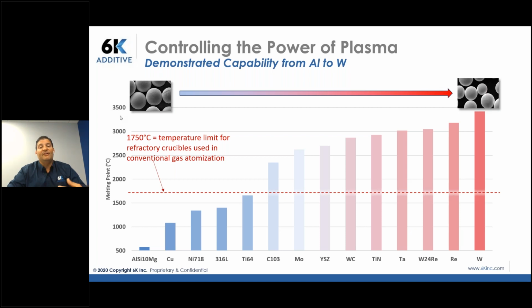And we can be successful with all of these because of that control that we have over the microwave plasma system. And there's a few different ways to control it. We can control the power, and we control the space where we actually inject the material into the plasma. But what it allows us is, again, anywhere from a very low melting temperature material all the way up to a very high melting temperature material to be processed through this system. So again, when you're thinking about material design or alloy design or what are the things that can be done, this gives you some idea of the wide range of materials that we can process on our system.